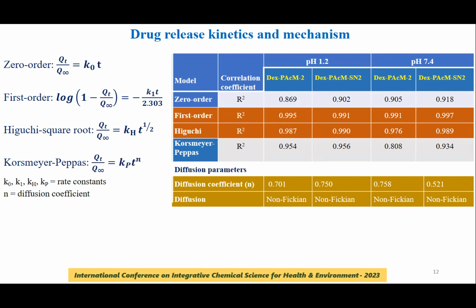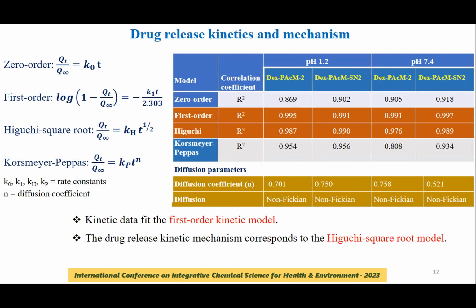The kinetic mechanism best fitted the Higuchi square root model, which indicates that drug release is controlled mainly by diffusion. Based on the diffusion coefficients, it was found that the drug release pattern follows non-Fickian diffusion. As you can see, the value of n is above 0.5 but less than 1. So this reflects non-Fickian diffusion, which means that both polymer relaxation and diffusion rate are comparable in drug release.